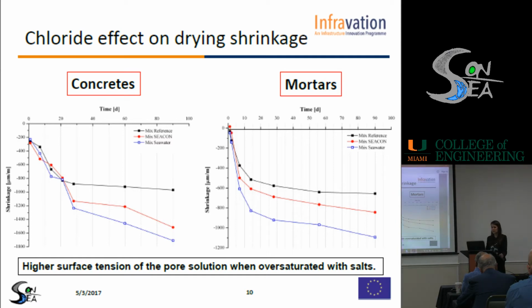The results are completely in agreement, so we can say that when we have a higher chloride content, the shrinkage is higher. So the chloride content worsened this behavior, and we thought that it was due to the higher surface tension of the pore solution when oversaturated with salts.